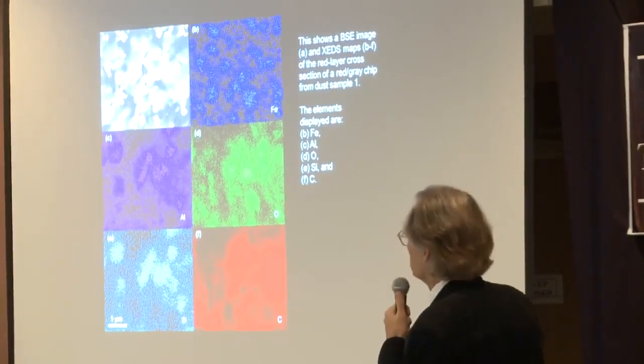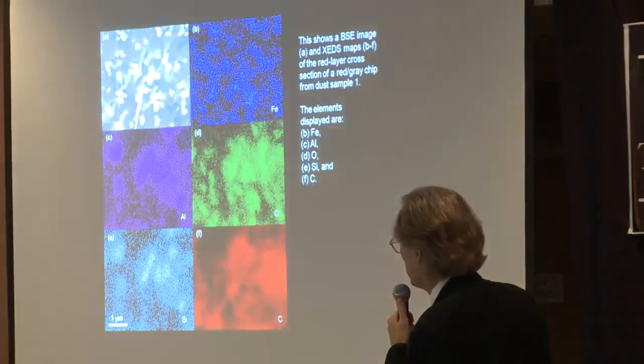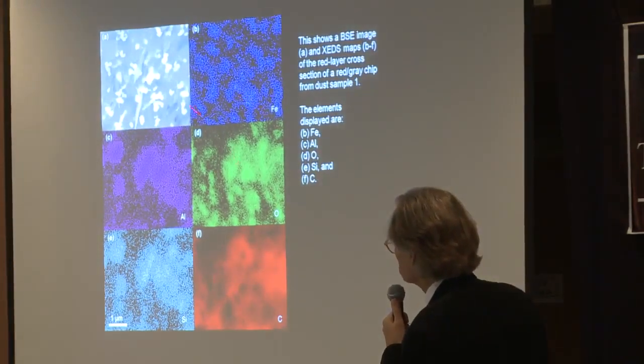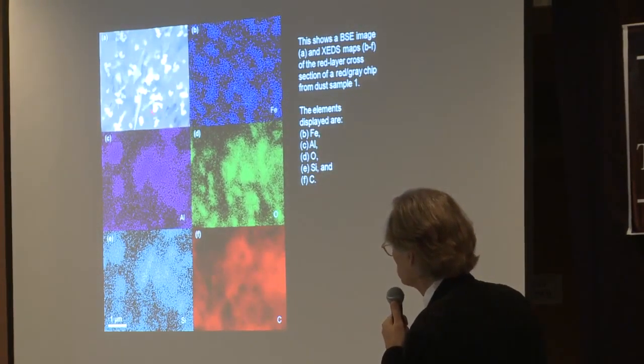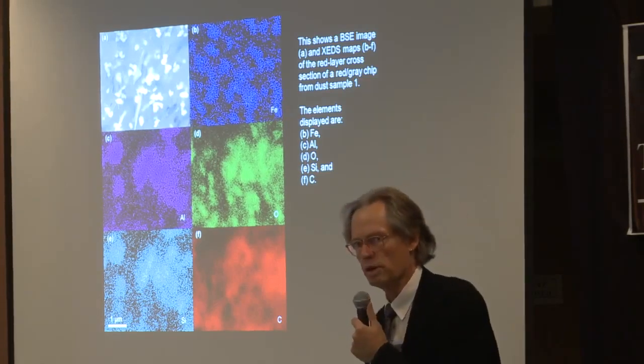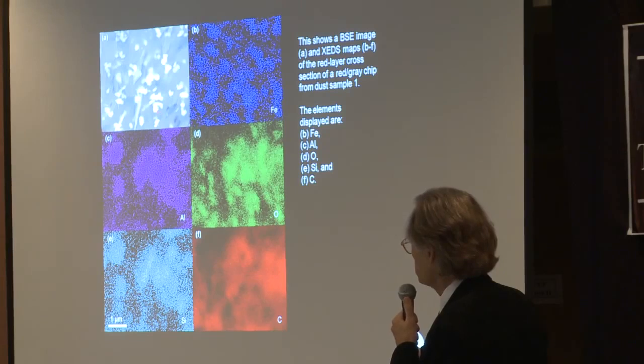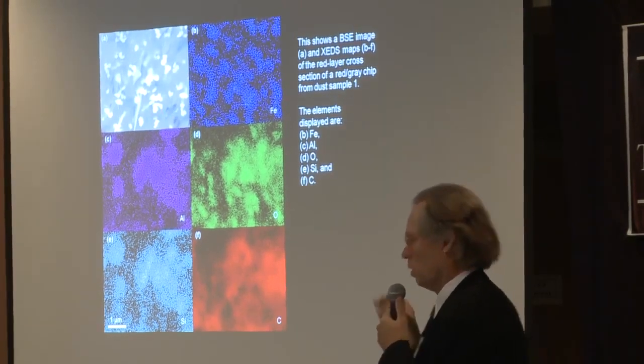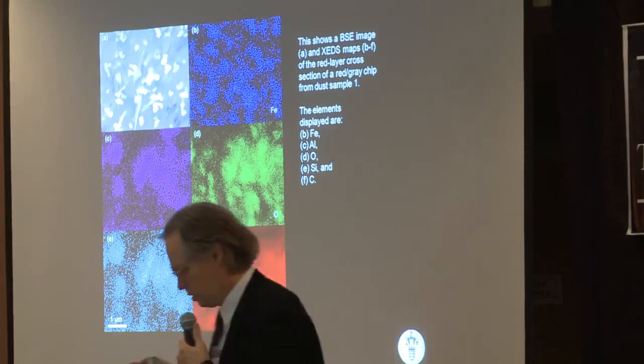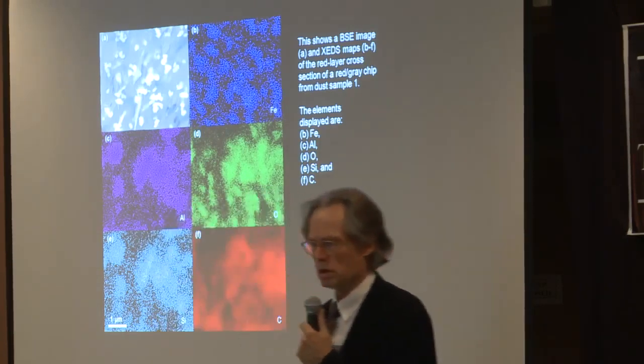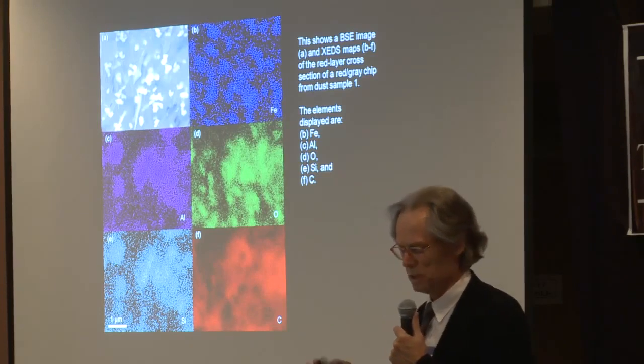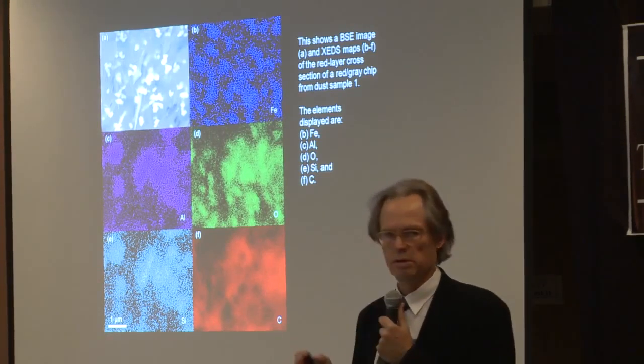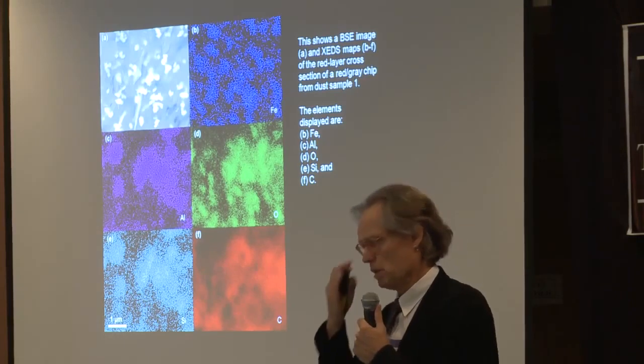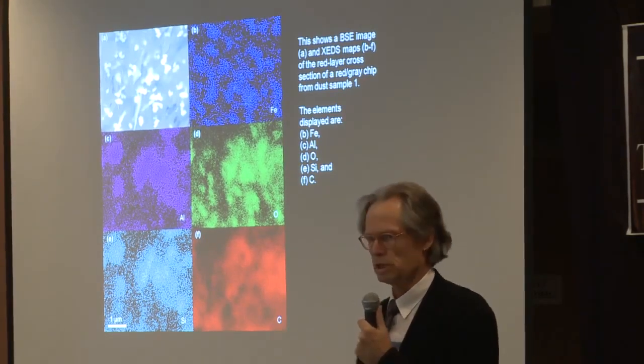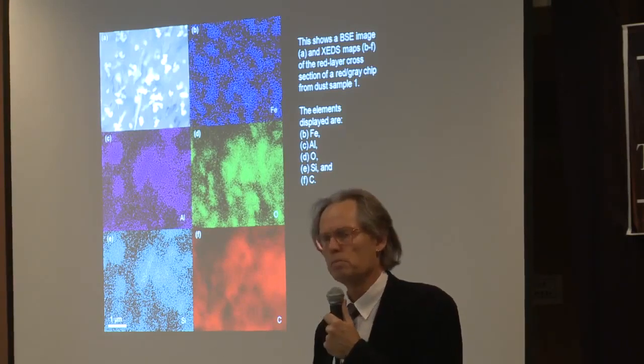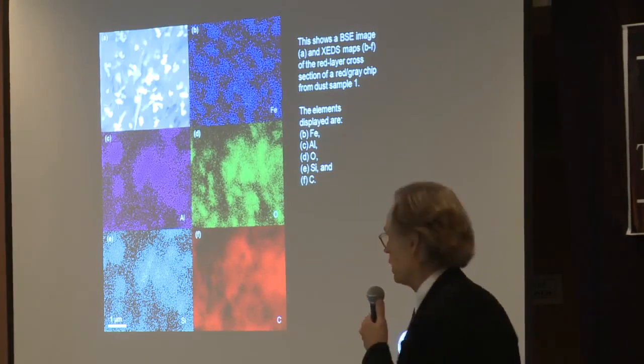flakes, which are seen here from the side, actually, while the iron and the oxide are located here in these small particles. And that is what it is. I can tell you already now, this white particle here is iron oxide. Now, one very important point here: is the aluminum bound to the silicon or isn't it? Because aluminum and silicon are very, very common elements in nature. The most common element on Earth is oxygen, number 2 is silicon, number 3 is aluminum, because they're omnipresent in stone, granite.